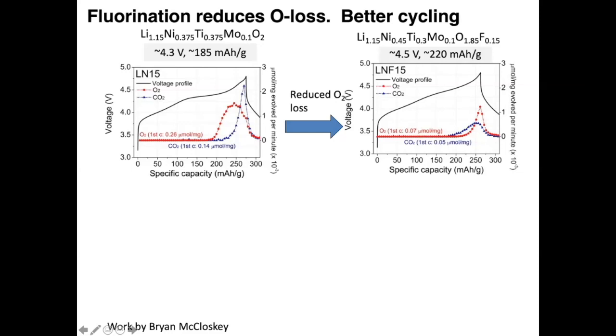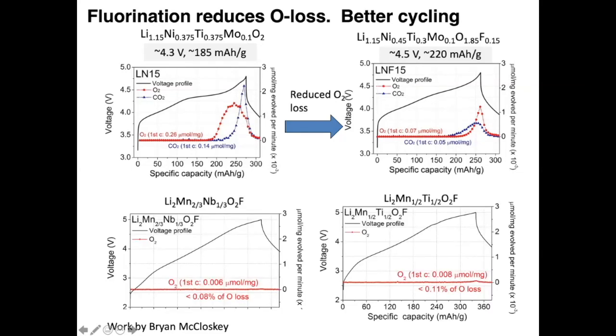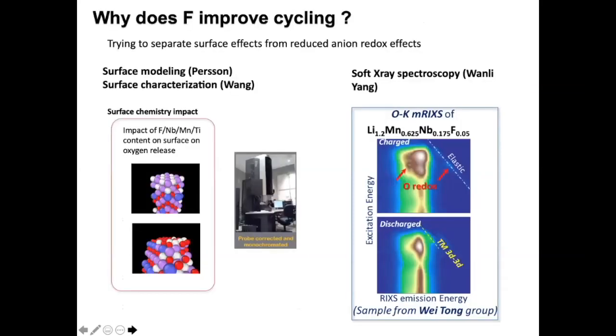I think what's even more remarkable is that when you go to high fluorination content, so these are materials that are 33% fluorine substituted, we charge to 5 volt and essentially no oxygen comes off whatsoever. Basically, there is almost undetectable oxygen loss. So clearly, fluorine stabilizes these materials, and we are not 100% sure exactly what causes this, but there is really nice modeling work going on.